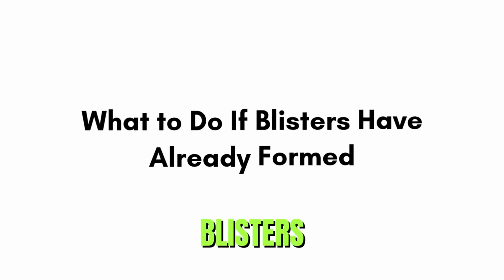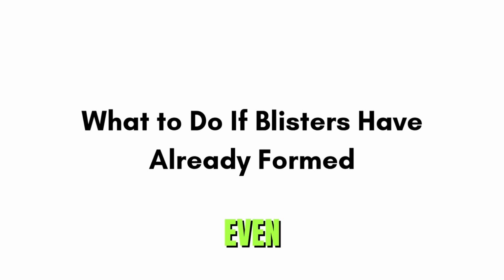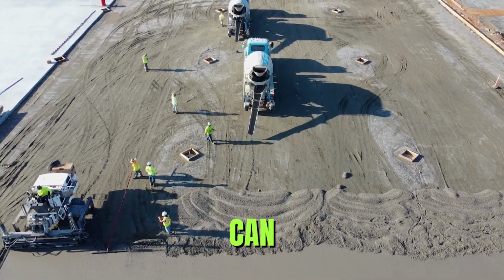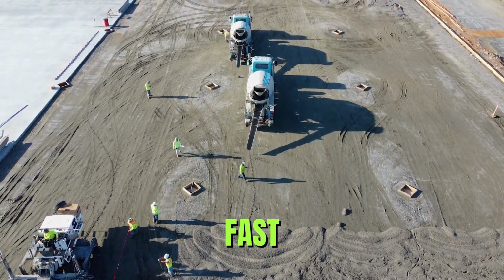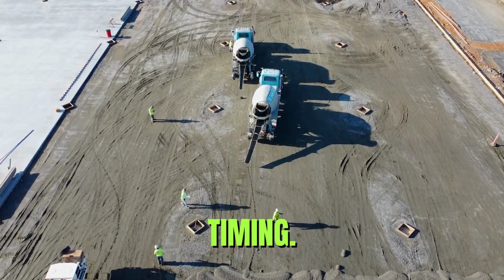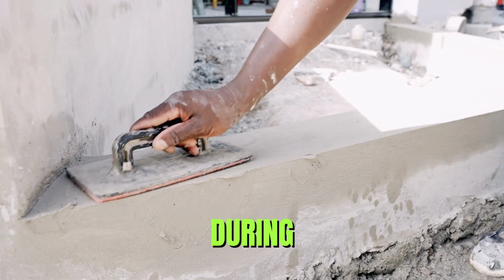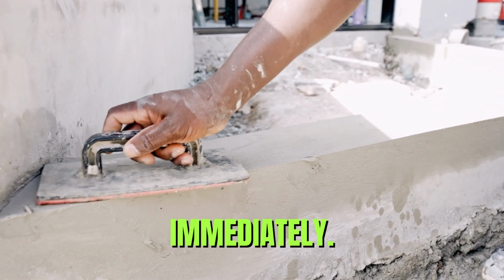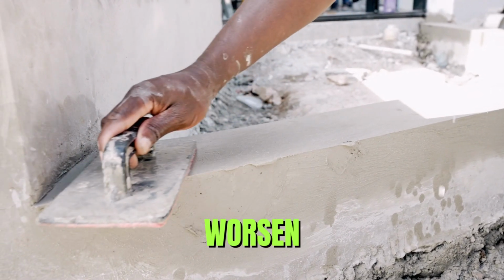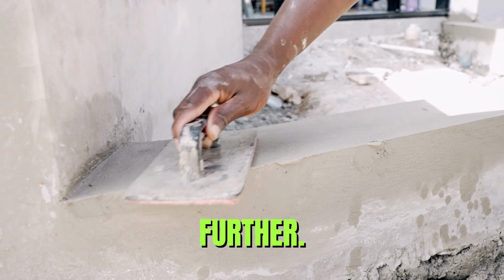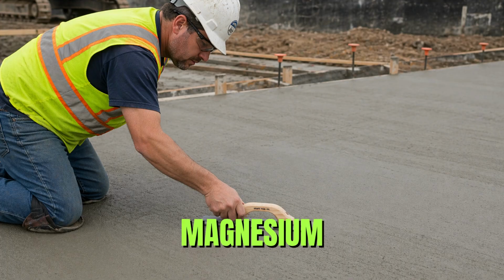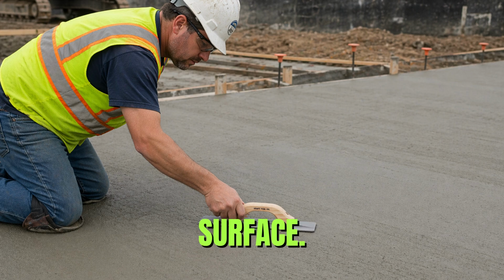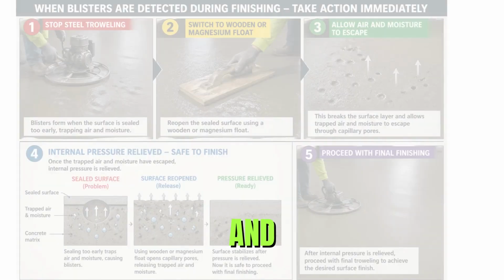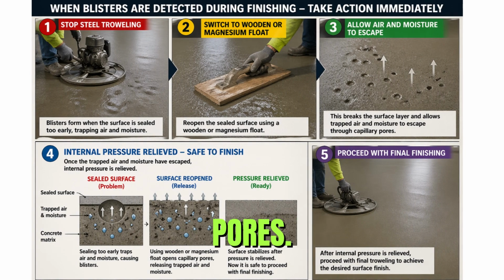What to do if blisters have already formed? Even with proper planning, blistering can still occur. The key is fast and correct action based on timing. If blisters appear during finishing, stop steel troweling immediately. Continuing will worsen the defect by sealing the surface further. Switch to a wooden or magnesium float and reopen the surface. This allows trapped air and bleed water to escape through capillary pores. Let the slab stabilize and only then proceed with final finishing.